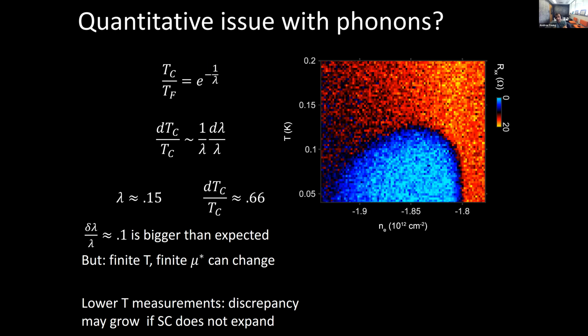There are some quantitative issues with this that we're still trying to think about. If you just look at the simplest picture here and ask, how much does TC change over what range of density, it doesn't quite make sense. It's surprising that if this is true, the density of states is not changing so rapidly that you wouldn't expect superconductivity to be much more ubiquitous than it is. We do see it over a relatively narrow range, but it comes down to some details of how correct is this formula, what things are missing. The Coulomb repulsion is not accounted for, and all these other things which we know are important.